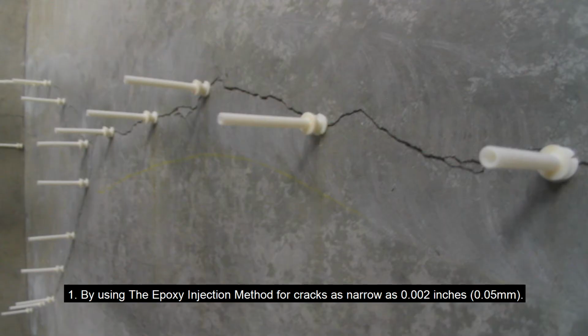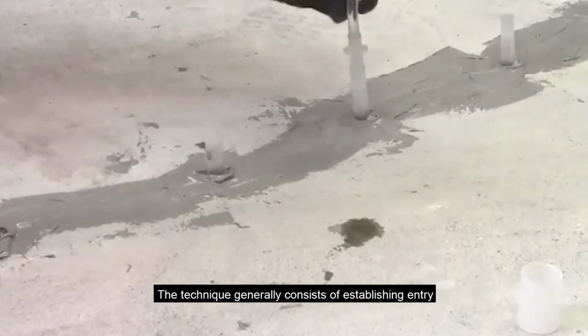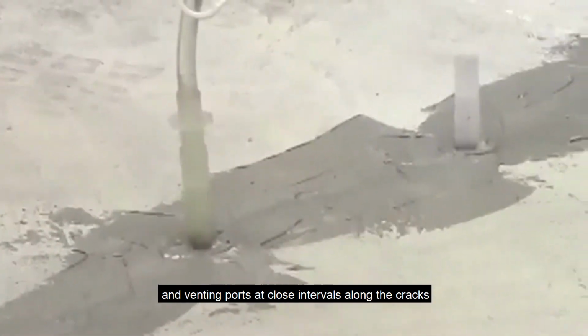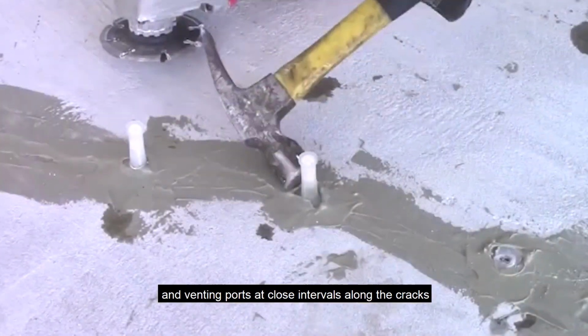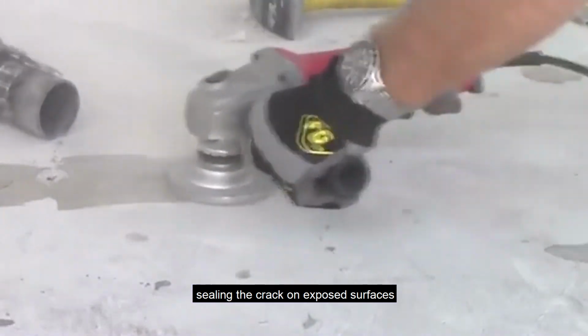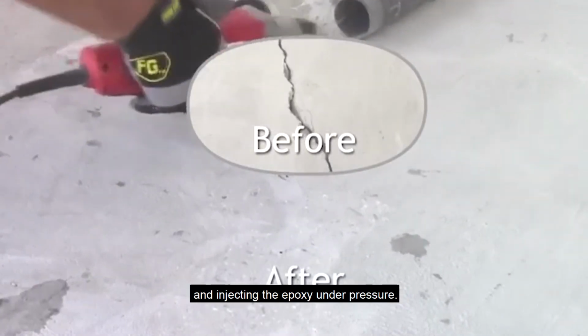1. By using the epoxy injection method for cracks as narrow as 0.002 inches (0.05 millimeters). The technique generally consists of establishing entry and venting ports at close intervals along the cracks, sealing the crack on exposed surfaces, and injecting the epoxy under pressure.